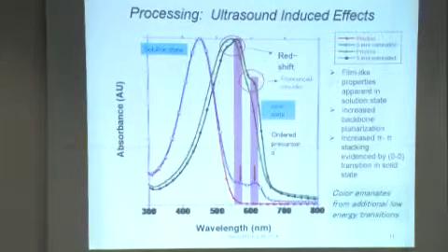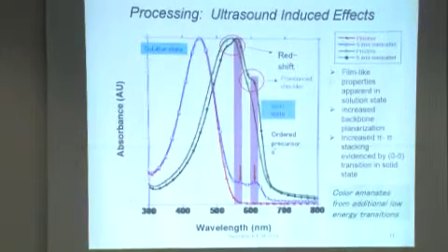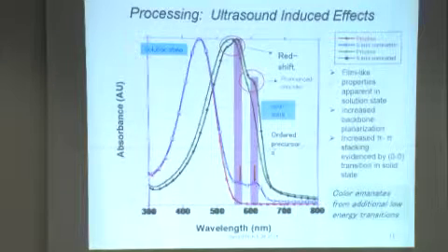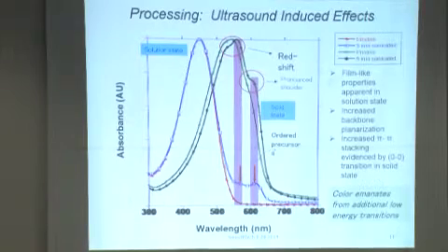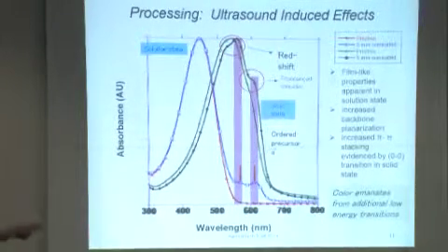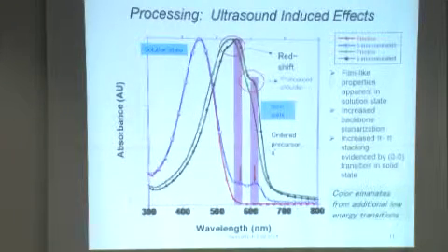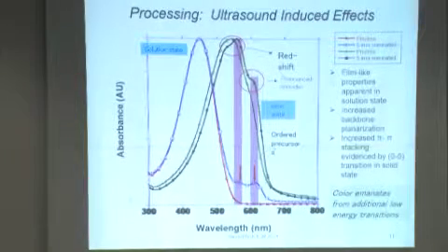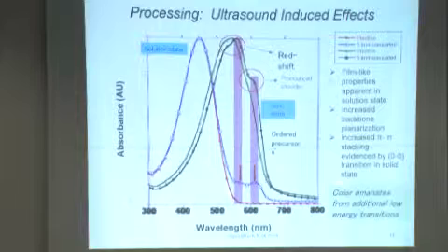But what we do see is that, whether it's in the solution state or the solid state, if we look at the films or the solutions spectroscopically, there are changes taking place in that material. We're starting to see bands in about the 600 nanometer region in the solution state that are reminiscent of some of the vibronic structure that we see in the solid films of that material after they're deposited on the substrate. So we're getting film-like properties in the solution state. That most likely is because we're seeing an increase in the planarization of the polymer backbone, and we're probably seeing an increase in pi-pi stacking of the polymer chains as evidenced by the vibronic structure.